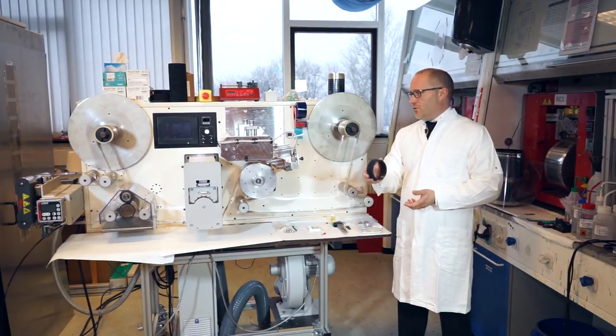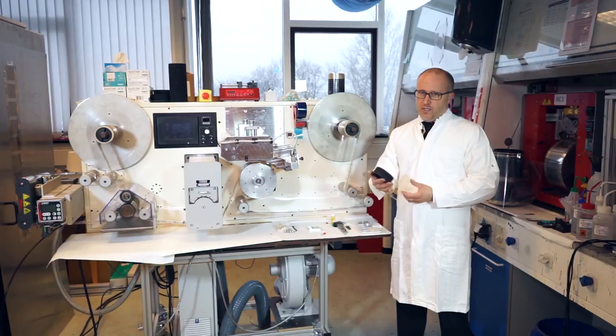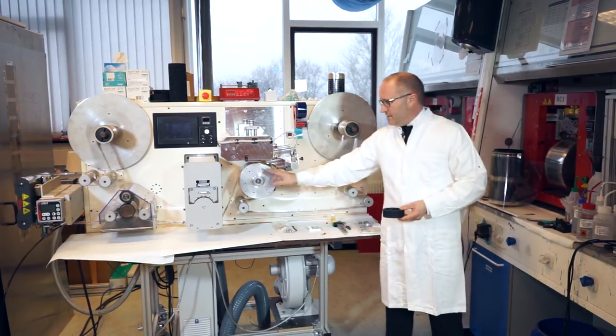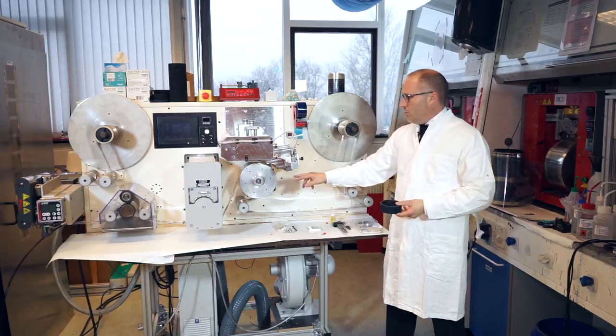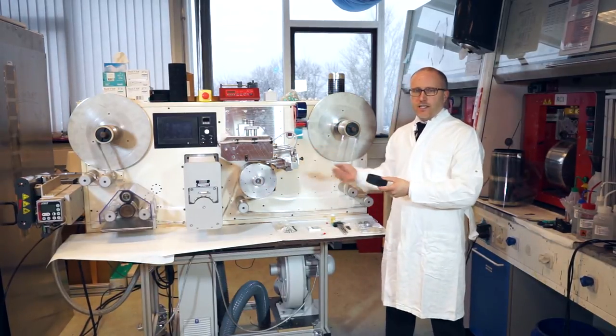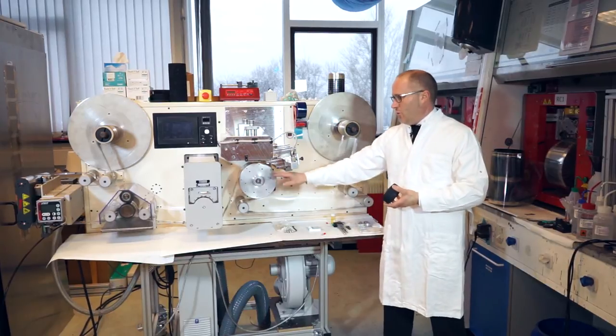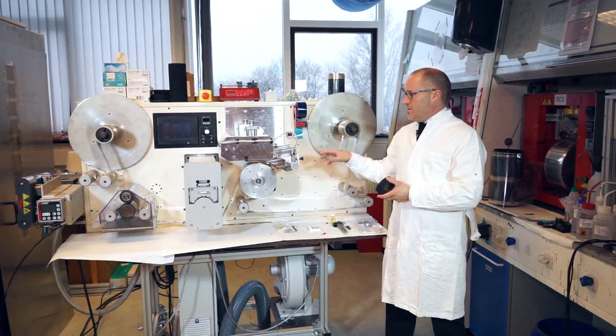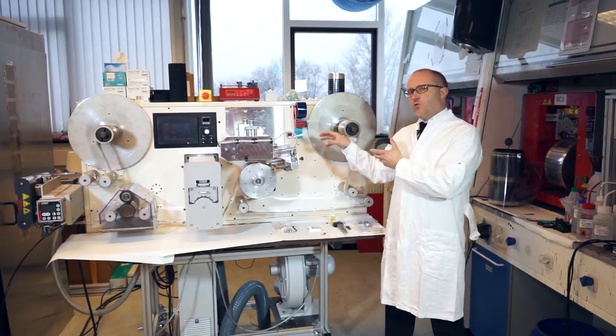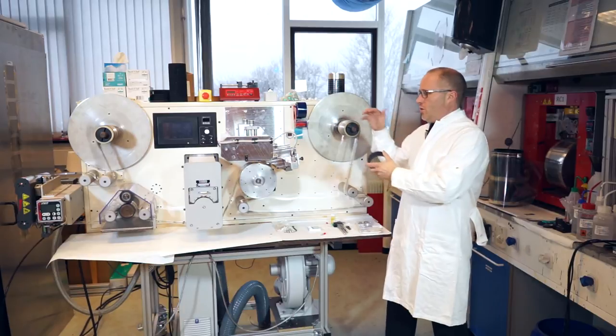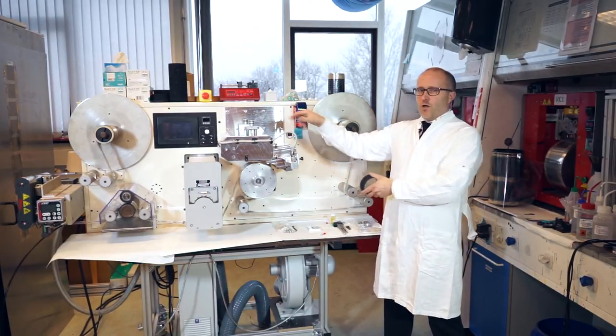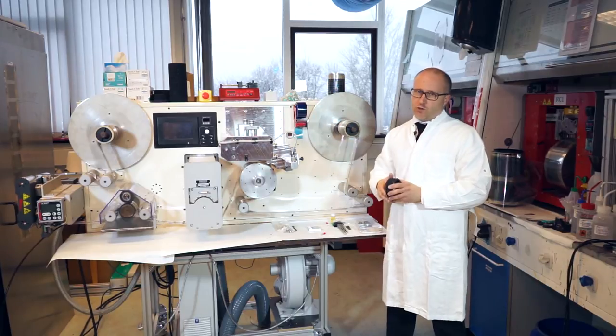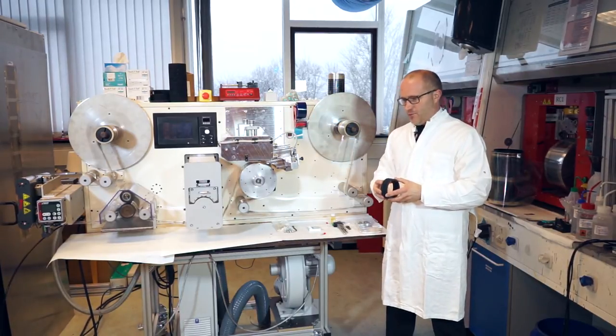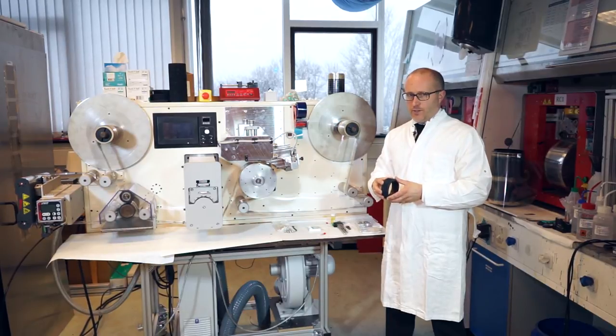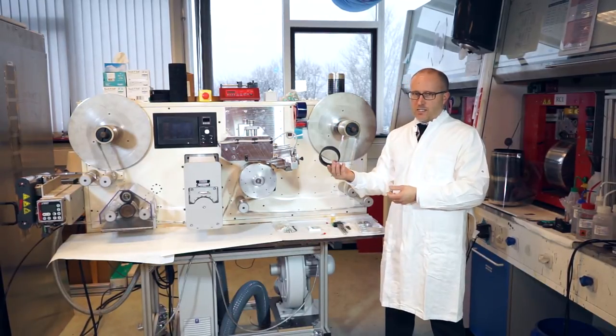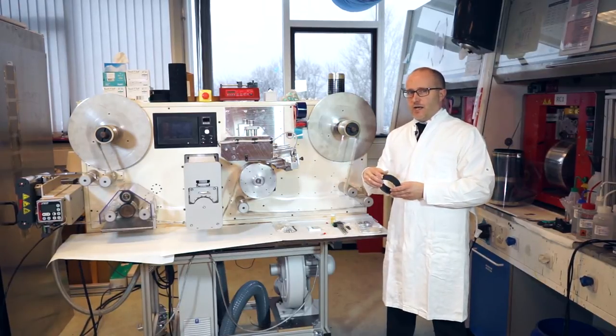An increased complexity is, of course, also in this flexo printing unit. In principle, you can operate this machine in a mini roll coater mode, where you simply wind the foil around, and in that sense, it's completely identical to the mini roll coater, except it's a smaller roll. And in practical terms, all this does is enable you to make sure that what worked on the mini roll coater also works on this machine before taking the larger step into the roll-to-roll transport. Now, an additional complexity was in this flexo printing, where on the mini roll coater, you could load a single cylinder with ink, and that would be enough for the 1 meter stretch that you have around the circumference.